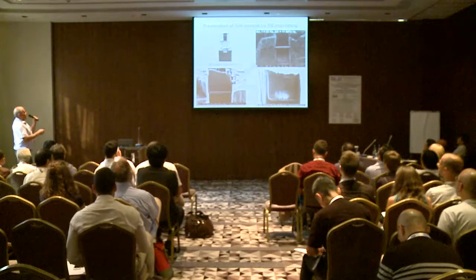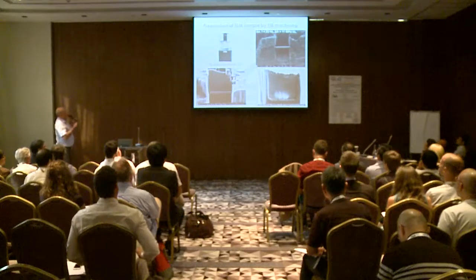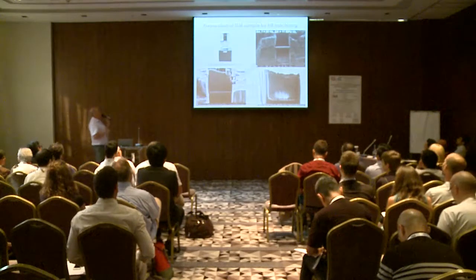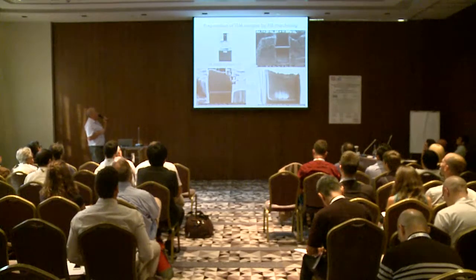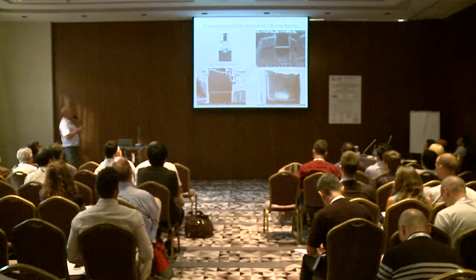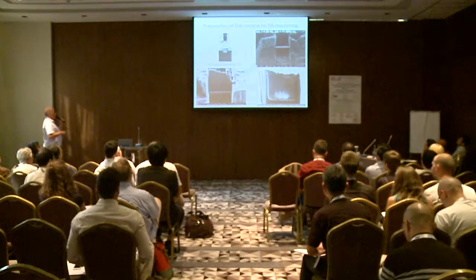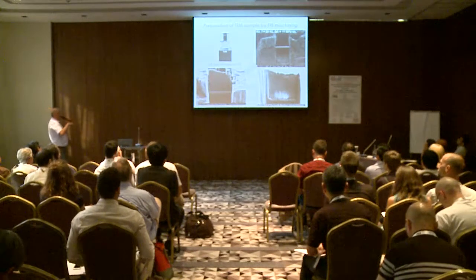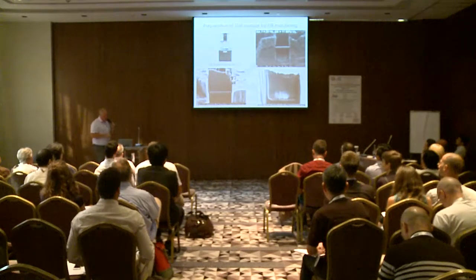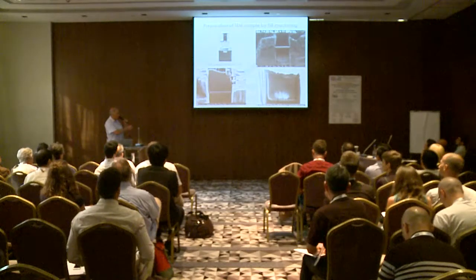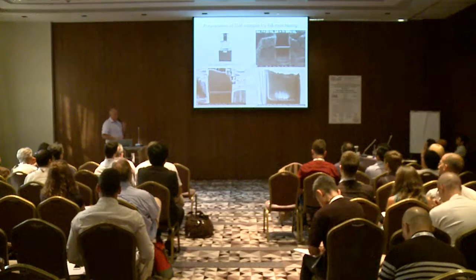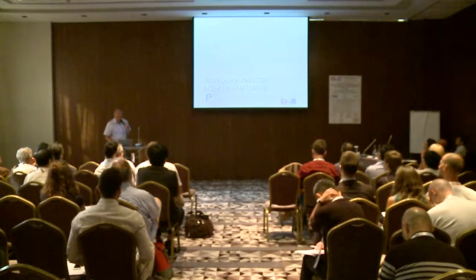In order to get further insights about the role of hydrogen on crack tip plasticity, by FIB milling we extracted some TEM foils from selected areas of the fracture surfaces.